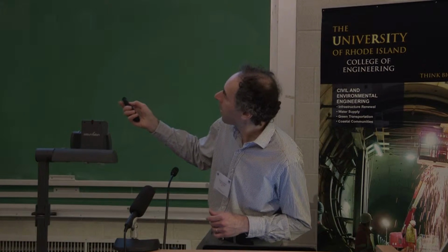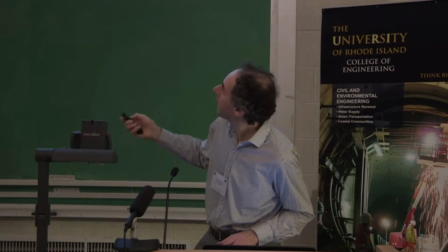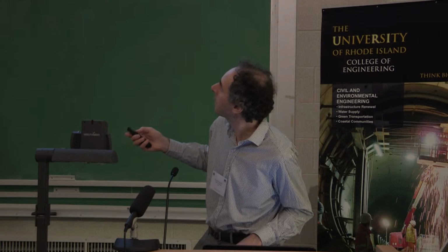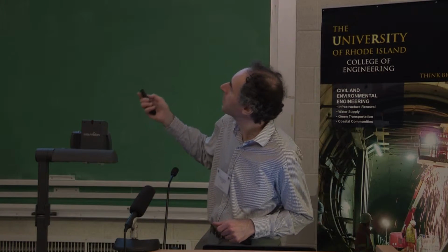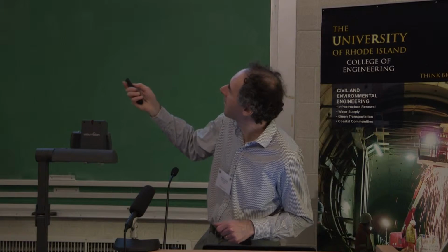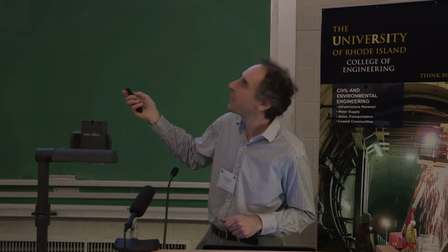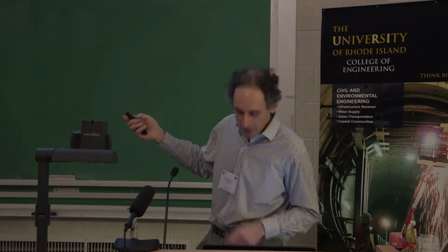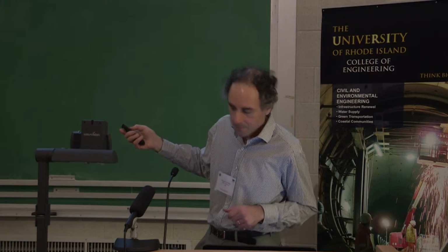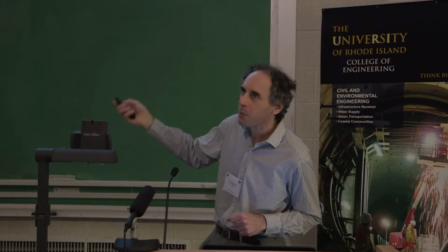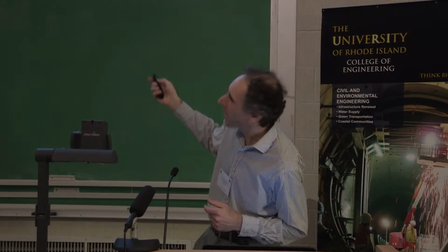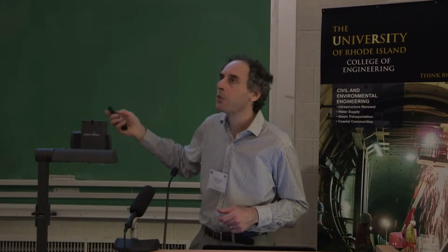These purple lines here are that same data of these, and what we're trying to show here is that we have a similar kind of shape. Our model is not exactly the same as some of these other asphalts, but it's on a similar scale. What's very different about these is that the real data span a wide range of frequencies of interest. In our calculations, because we have just such short times, we're limited to extremely high frequencies. And so we do our comparisons at higher temperatures and then do a lot of time temperature superposition to be able to make this kind of comparison among different systems.